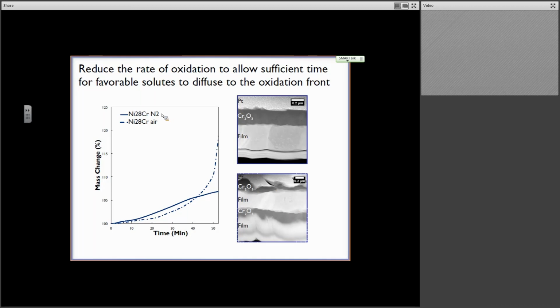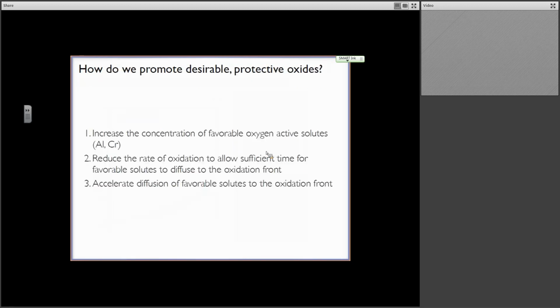And this is just a matter of the relative rate of oxidation, right? And so we talked about that was our second strategy. So the first strategy is change the chemistry. The second strategy here is to change the rate of oxidation. And so we can see that here. So we actually heated at the same temperature, the same rates, but we changed the partial pressure in our environment, and we got vastly different outcomes. Again, we kind of know this. This is used in a number of applications. Now the third one is to accelerate the diffusion, and this is one that is not as commonly explored.